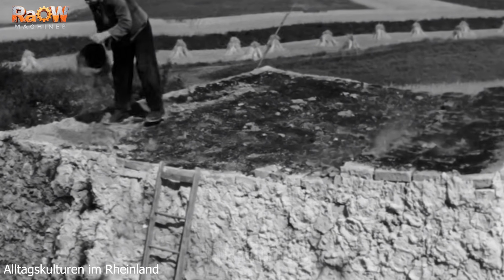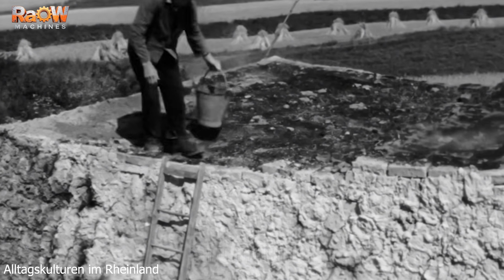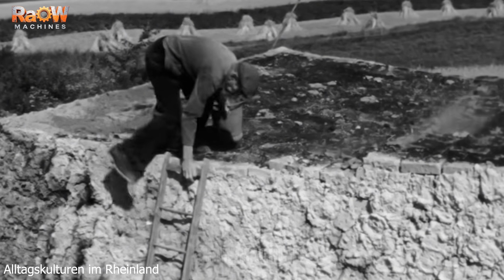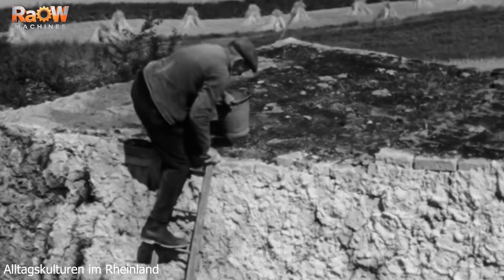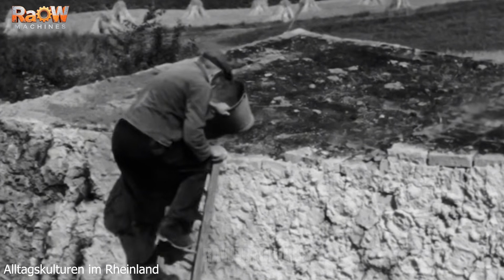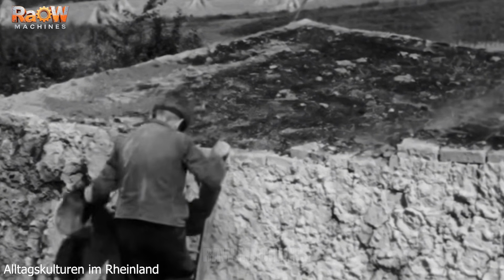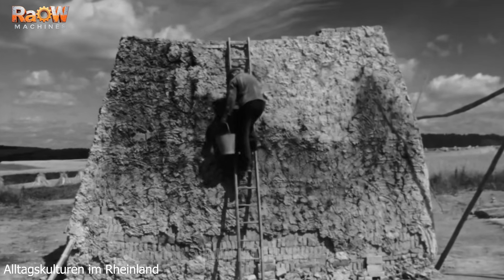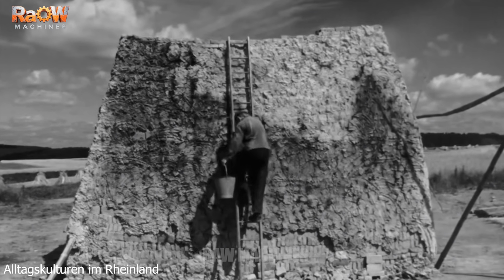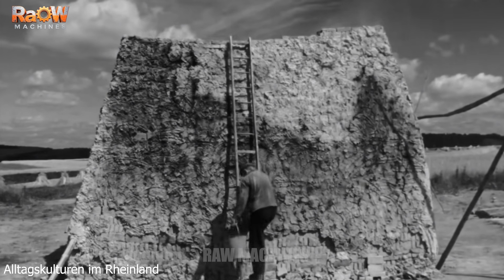When higher temperatures were required, the fire channels were opened to intensify combustion from the base, raising the temperature to around 1,200 degrees. At this stage, the kiln crown and other hot spots were covered with additional clay to retain heat and prevent the fire from flaring out of control.